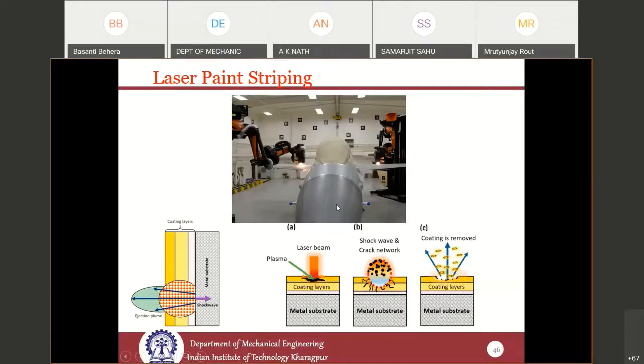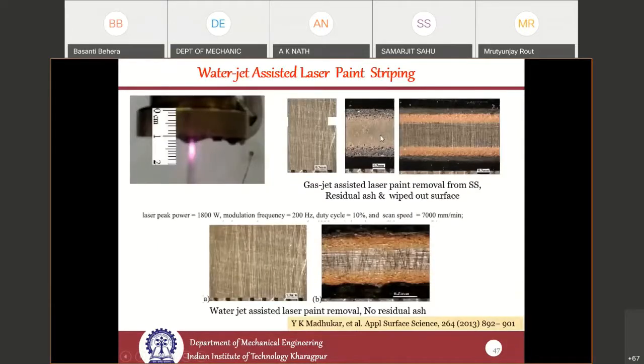Many times, it has been seen that when you use air or a gas jet for this, there is a lot of burnt ash from the paint that remains, which needs additional mechanical means to remove. But when you use water-assisted paint removal, you don't need any secondary process to remove the ashes, and you can get very good quality paint removal without damaging the surface beneath.